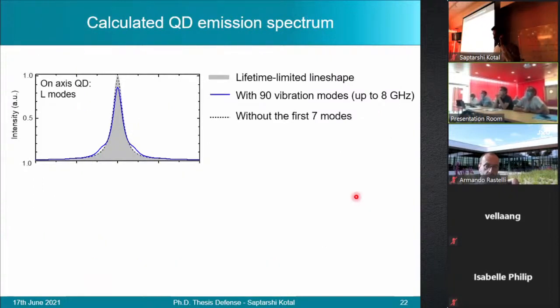Now, the complete quantum dot emission line shape was calculated by combining the contributions of every individual mode. Here I represent a quantum dot, which is precisely positioned on the axis of a needle nanowire. Such a quantum dot would experience only the longitudinal modes. And we plot here in gray the radiatively limited line shape. And as you can see, by considering modes up to a frequency of 8 gigahertz, we have the blue curve. Clearly, the vibration modes have a significant effect on the line shape.